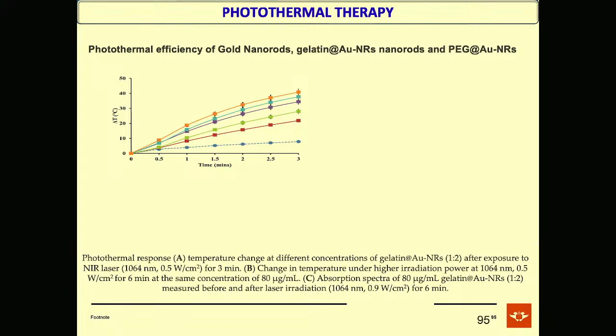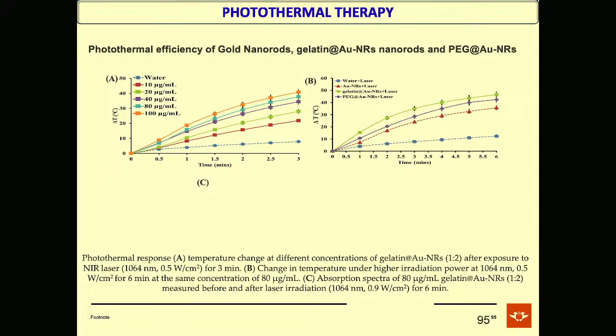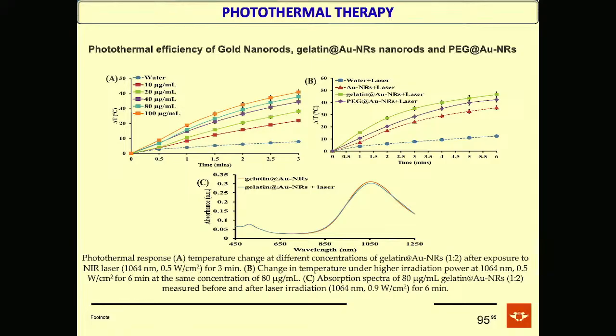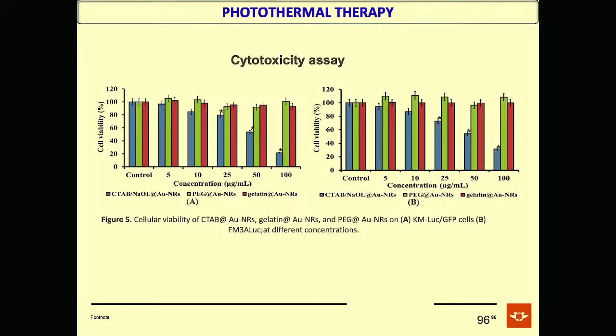Now, we test this with what people have done. This is the normal material, the gold itself. This is when you use PEG, and this is when we use our material. Another thing that we decided to test is, by the time we use this material, can we reuse it again? We discovered that the material still maintains its property after we have used it with the heat. And this is just for the cell work.